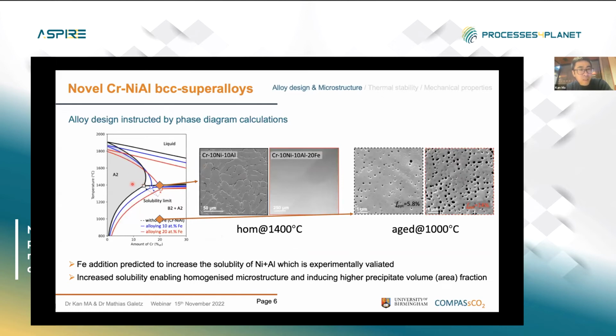And one way, instructed by the calculation, is that we can add iron. So here we show in black line the phase diagram with zero iron, so without iron, and with 10 atomic percent iron and 20 atomic percent iron. And we can see the solubility limit. The single phase area expands to the right, so it has a larger area, which is supposed to increase the solubility.